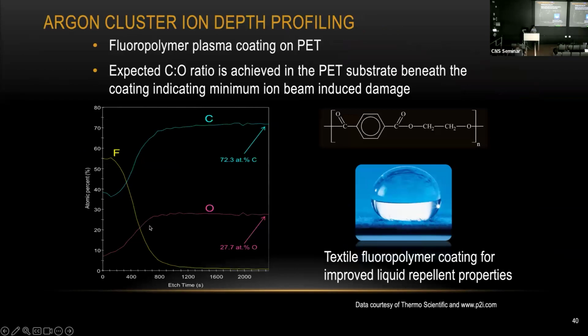And we can also do depth profiling using the argon cluster source. Earlier I mentioned the cluster source gives you much gentler etching, which means the etch rate will be much slower. So this is again the PET sample, but on top of the PET sample we have a fluoropolymer coating. Again, the signature for the fluoropolymer coating is the fluorine. So that's why we go ahead and do some measurement and etching using the cluster source.